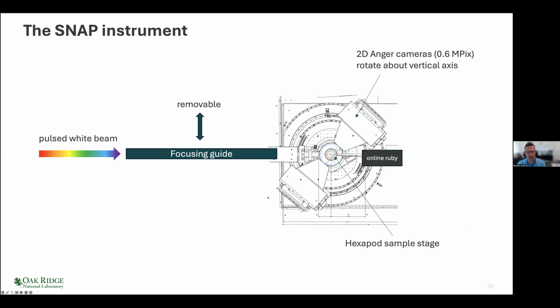This schematic shows some of the elements of the instrument. So coming from the left, we have the pulsed white beam. That passes through a focusing guide, which can be removed if we want. So that allows us to exchange divergence for flux. So if you want to have sharper Bragg peaks but lower flux, we can do that, or vice versa, we can also do that.